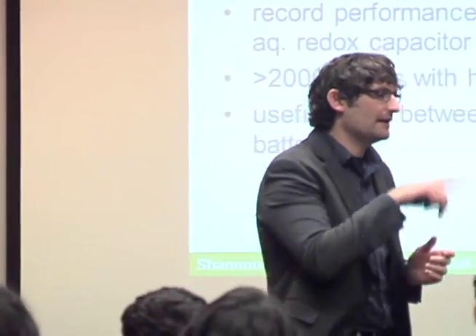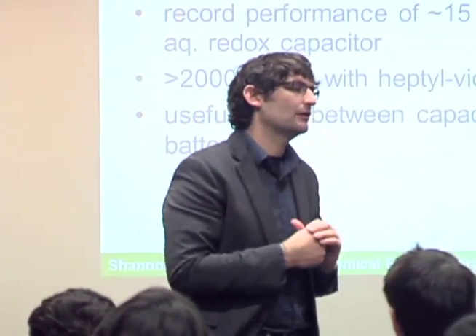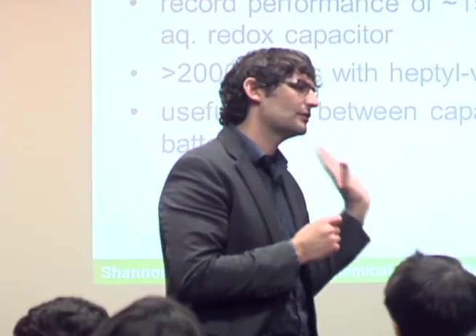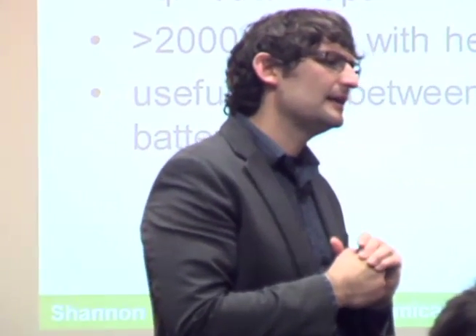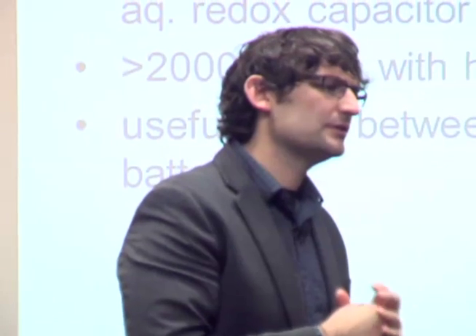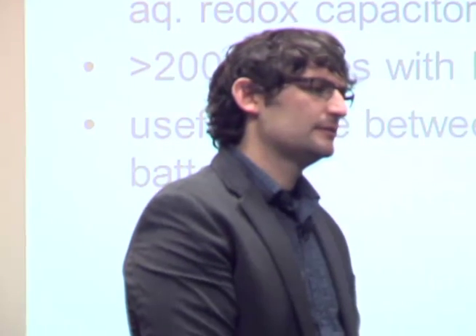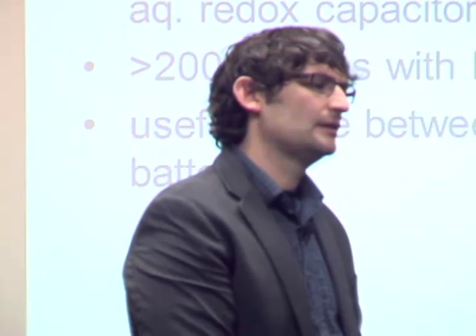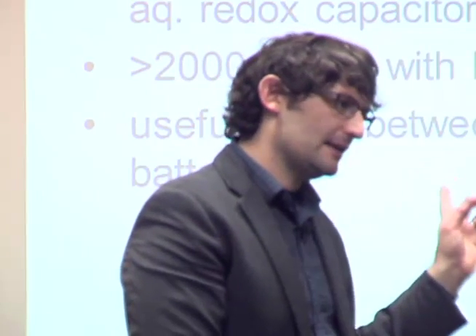Did you measure the bulk resistivity of the carbon electrode and the contact resistance with the current collector? Yeah, so we have that data. I don't have it off the top of my head, but we definitely have the impedance data and the bulk electrode resistivity data at the current densities we're operating at. Those don't appear to be huge components. So at low current density, that is not a factor.